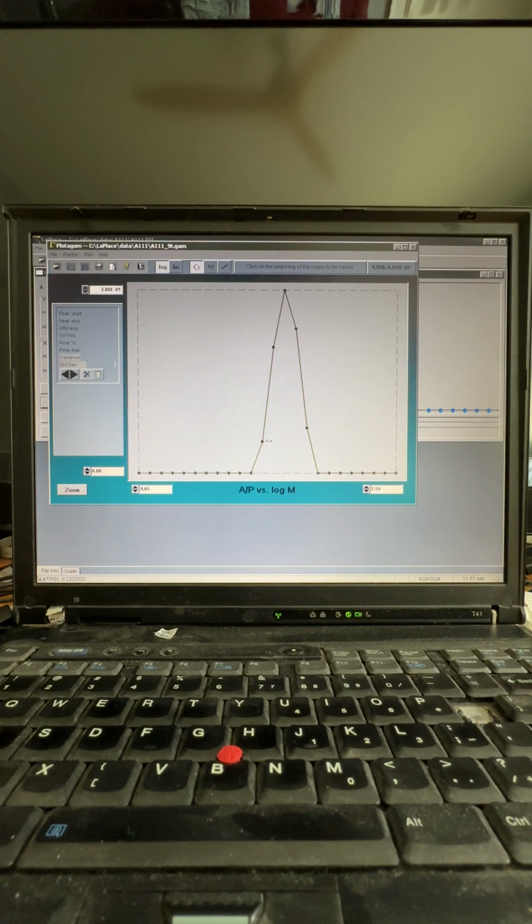This is a good time to point out, you can barely see them here. Go back to better pointing mode. You can barely see a little bit of red here. These are the error bars. Nobody ever talks about the error bars, but CONTIN gives you error bars on each of its points. So that's actually worth knowing. And you can barely see them, but oftentimes they're much bigger than that. On a weak, small peak, they're sometimes more obvious, and probably that peak might not even be significant at all. So that would be a great reason to trim it.